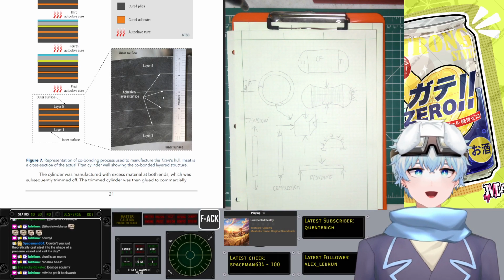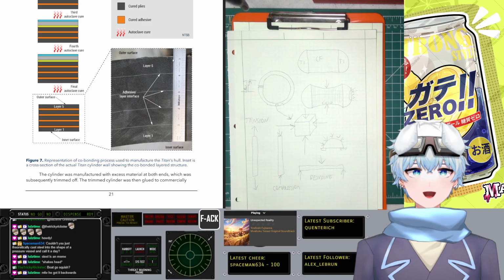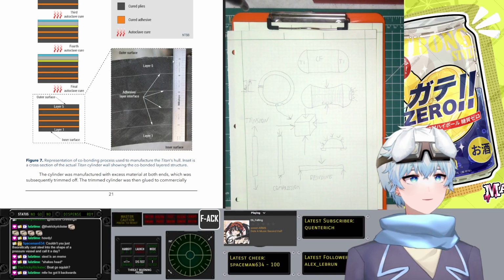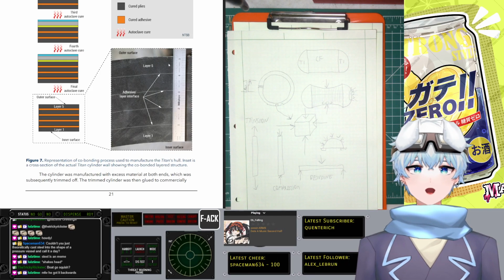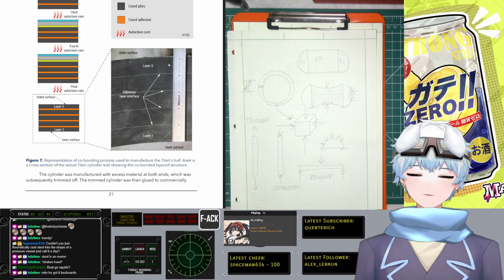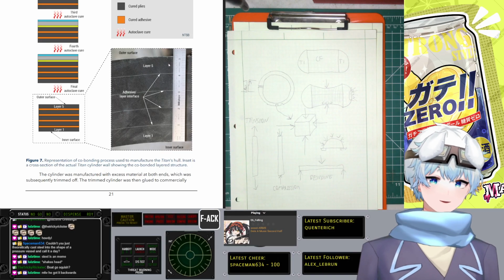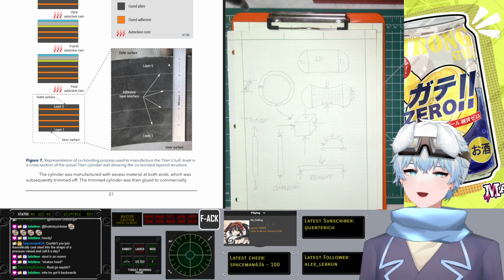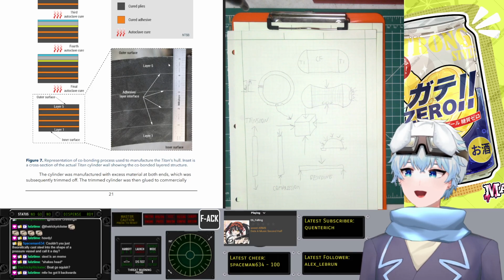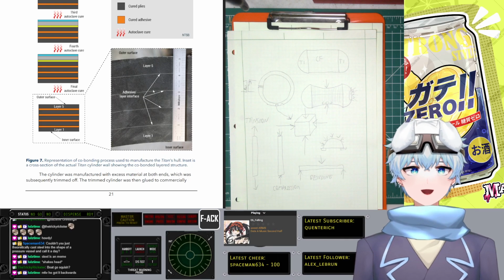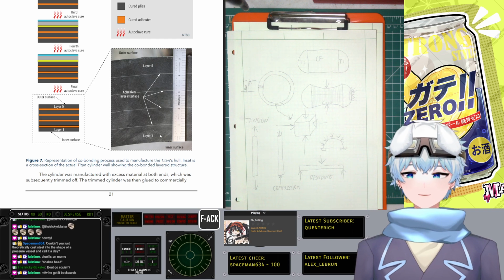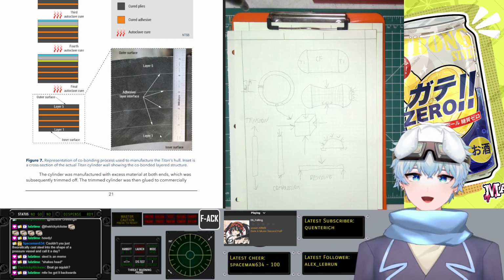And so we see that, well, first off, this is a hair over 5 inches. Actually, this looks like maybe about a 1/4 inch over 5 inches. So it's thicker than it was designed to be. That's kind of a problem. But then also, it's 5 distinct layers. That's really not good.